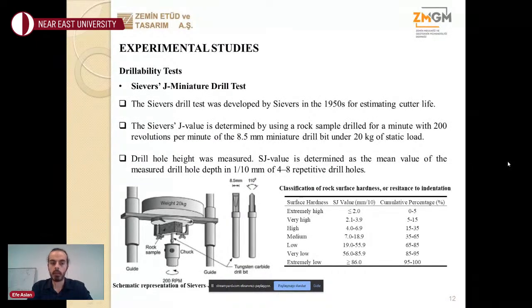To begin with, we need to identify the Sievers J value by conducting the miniature drill test. It was developed by Sievers in the 1950s for estimating the cutter life, and the J value is determined by using a rock sample drilled for a minute with 200 revolutions per minute of the 8.5 millimeter miniature drill bit under 20 kilograms of static load. The drill hole depth was measured. The J value is determined as the mean value of the measured drill hole depth in 1 over 10 millimeter of 4 to 8 repetitive drill holes. You can see on the left corner the schematic representation of this equipment. On the right-hand side, you can see the classification of rock surface hardness or resistance to indentation values.